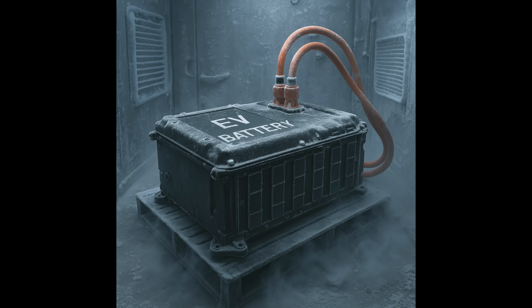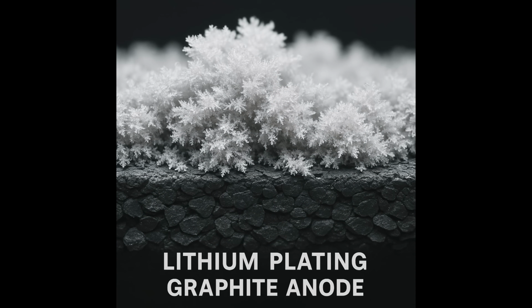Imagine stirring syrup straight out of the fridge. Now imagine lithium ions trying to flow through that thick syrup. During charging at low temperatures, especially with high currents, lithium ions cannot intercalate into the graphite anode quickly enough. Instead, they begin depositing as metallic lithium on the anode surface. This is known as lithium plating. Plated lithium is electrochemically inactive, which reduces capacity. Dendrites can form, which means it risks internal short circuits and overheating that can lead to thermal runaway. And it is irreversible. Once it forms, permanent battery degradation occurs.